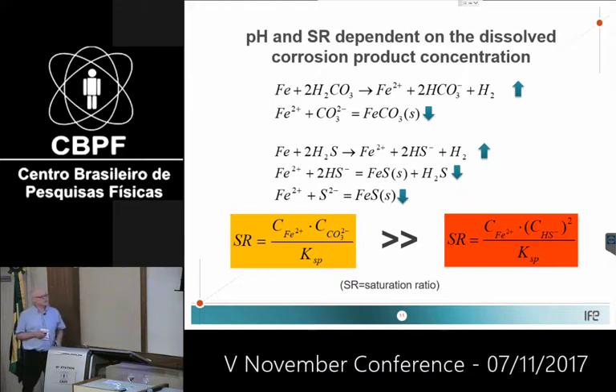It's a lot of reactions going on. You have iron reacting with the CO2 or carbonic acid in the solution, and then you produce iron ions and bicarb, and the pH goes up. When you have enough iron and bicarb, you start to precipitate iron carbonate, then pH goes down.